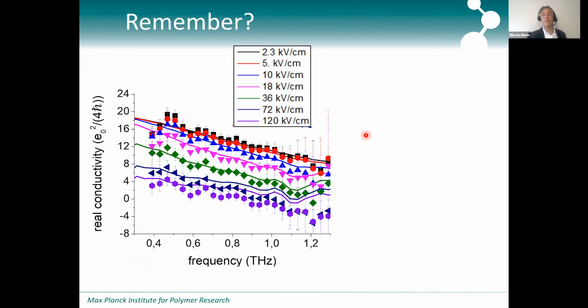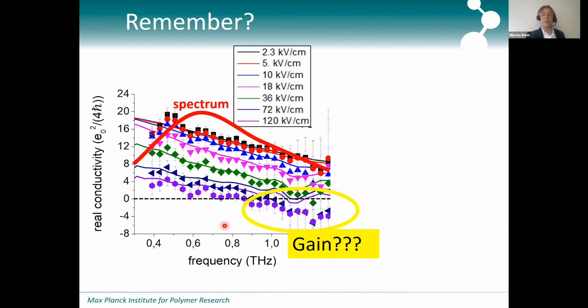And so coming back to our original measurements, this explains the gain that we have here, because our spectrum in these experiments actually peaks at about 0.6 terahertz. So the spectrum kind of looks like this. It tails off to higher frequency. And so we now understand that we were generating the second harmonic of this 0.6 terahertz, and we're depleting this spectral region here and making, with some degree of efficiency, these higher harmonics that you see here show up at around 1.2 terahertz. So there is indeed, this is the actual spectrum. So there is indeed some gain.